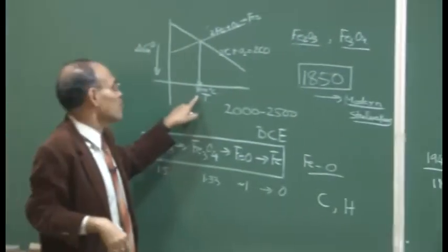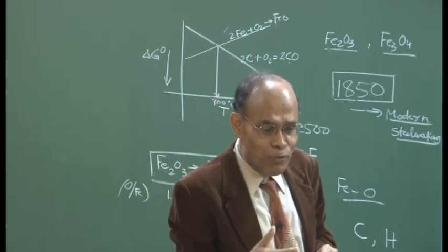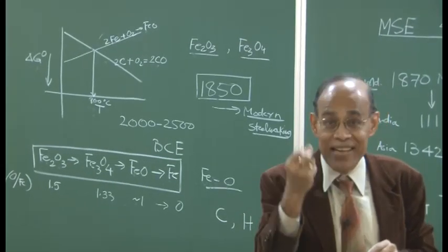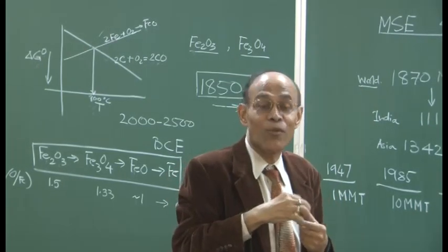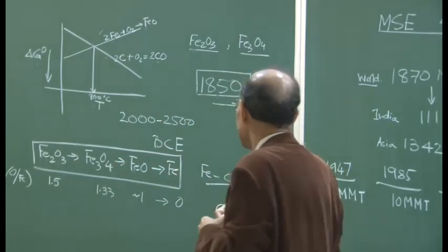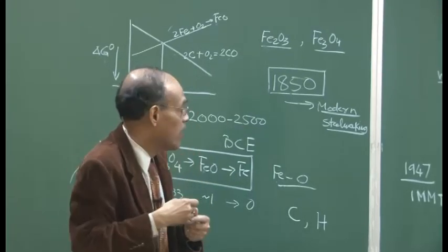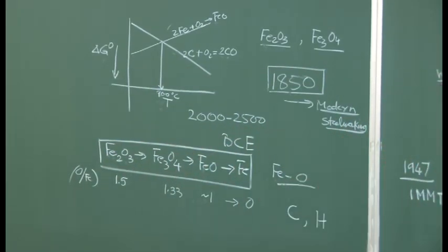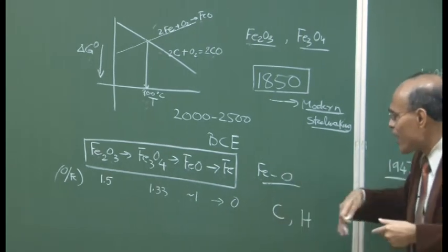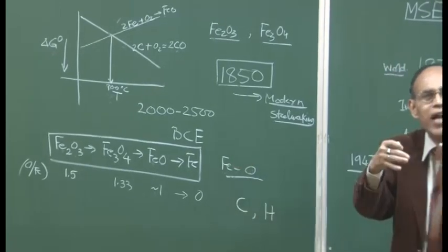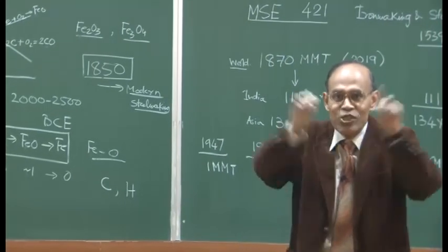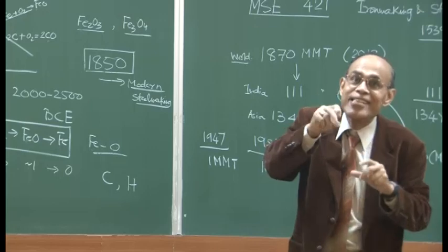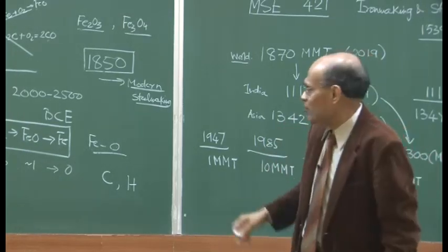They had difficulties in getting to a temperature of 900 degrees centigrade, which essentially tells us that primitive people 4000 years back were not in a position to extract iron in liquid state at all, because extracting iron in liquid state will necessitate a temperature of 1500 degrees centigrade. When people were struggling to create a temperature of about 900 degrees centigrade, forget about that. So the liquid iron production came much later. Primitive men basically produced what is known as wrought iron. When they mix carbon with iron oxide, some carbon escapes as carbon monoxide, but some carbon also mixes with iron. The iron becomes porous because the oxygen has left the iron ore matrix, and in those small tiny pores, the carbon particle gets in, and the iron that you get is basically an alloy of iron and carbon. That's what primitive people were producing.